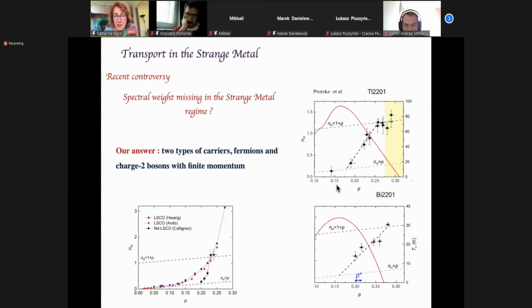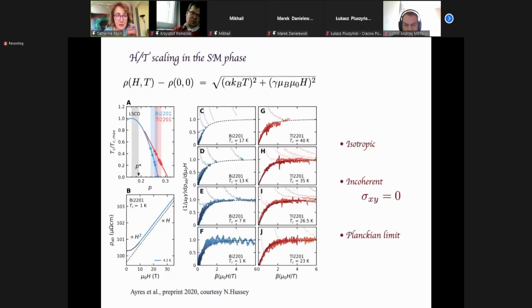So the group by Nigel Hussey told us, maybe we have another type of carrier, which will be seen for this very gradual change going from p to 1 plus p over there. So this new type of carrier should have H over T scaling. It's isotropic in B. It's incoherent, so it doesn't participate to sigma xy. And it has a Planckian limit, namely, it participates to the linear in T resistivity.